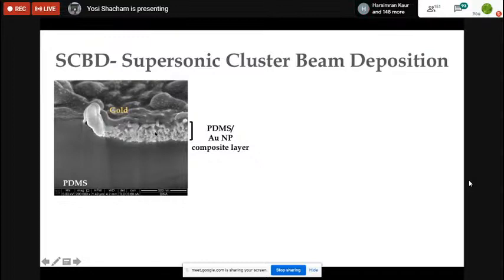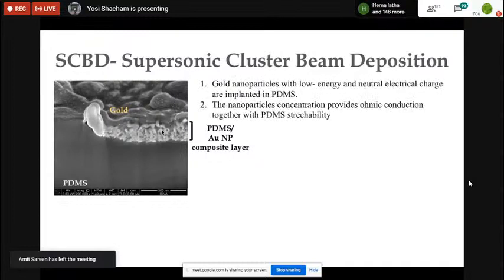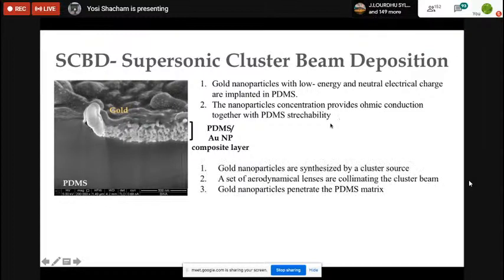And what happens is this is a very, very flexible material. The gold nanoparticles with low energy and neutral electrical charge are implanted in PDMS. The nanoparticle concentration provides ohmic conduction together with PDMS stretchability. And actually, there's even a company now in Italy making and selling this technology.